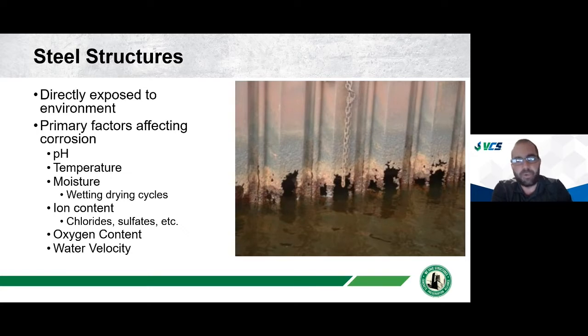Temperature and pH of the water are obviously important. Higher temperatures allow the corrosion reaction to happen much faster. Although, kind of interestingly, if you have a higher temperature of water, it holds less oxygen. So colder water holds more oxygen than hot water, and higher oxygen content allows corrosion to occur faster than lower oxygen content. So as temperature rises and oxygen content falls, it kind of has a balancing effect.